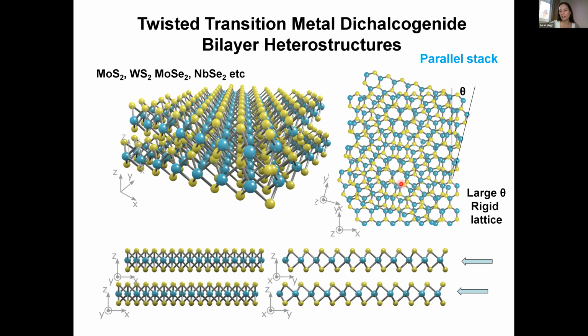So this is with no reconstruction and a relatively large twist angle, but just to illustrate the different types of stacking that we see. We have regions where we have chalcogen on chalcogen, chalcogen on metal, and metal on chalcogen. We get the general idea. We can classify these metal on chalcogen on metal as being the traditional 3R type stacking that we expect in these systems. And then we also have these chalcogen domains, which we know are unfavorable.